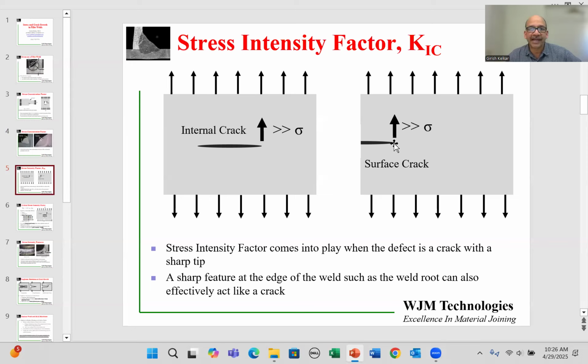Same is true with the surface crack. Even with the surface crack, the stress is going to be many times the applied stress. So the stress intensity factor comes into play when the defect is a crack with a sharp tip. So the difference between the stress concentration factor and the intensity factor is that the intensity factor comes into play when the feature is such that it effectively is a very, very sharp crack or crack-like feature. And that can be actually a crack itself or the weld root. And I'm going to show you schematics of that later as well.